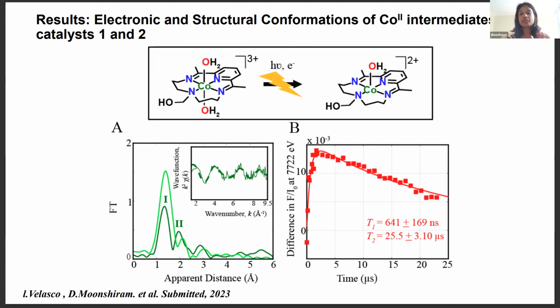And just by looking at the different bunches from 153 picosecond all the way to a microsecond, we have this data available for free at what was previously 11 IDD. We can monitor the time frame of formation, so the electron transfer to form the cobalt-2 species, as well as its decay back to the ground state.